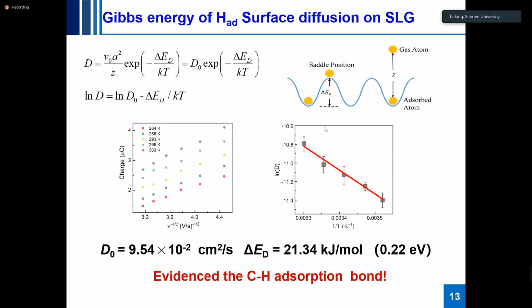And from the Arrhenius equation, we can perform the experiment at different temperatures, plotting the logarithm of the surface diffusion coefficient against the reciprocal of the temperature. We can figure out the Gibbs energy of the surface diffusion. This is very small, like 21 kilojoule per mole. This value is much lower than the carbon-hydrogen bond. So this is also evidence that it is actually an adsorption bond.